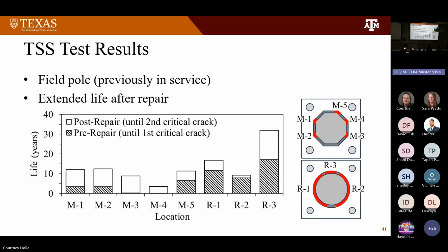In the plot, we have 2 types of sections. The hatched section represents the pre-repair life, which is from the start of the test until the occurrence of the first critical crack on the connection, on the weld. And this clear section represents the post-repair life, which is from the moment of the repair until the occurrence of the second critical crack on the connection. It could be a little bit alarming that when we see the pre-repair life, the hatched section is remaining less than 20 years or even less than 1 year. But when we consider that these poles are from the field and they were in service previously, that would not be that surprising.